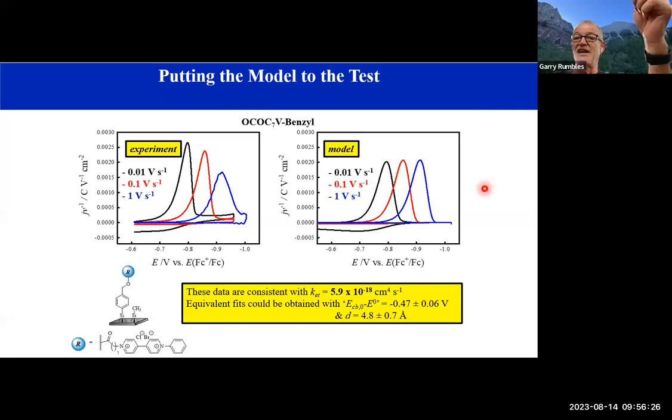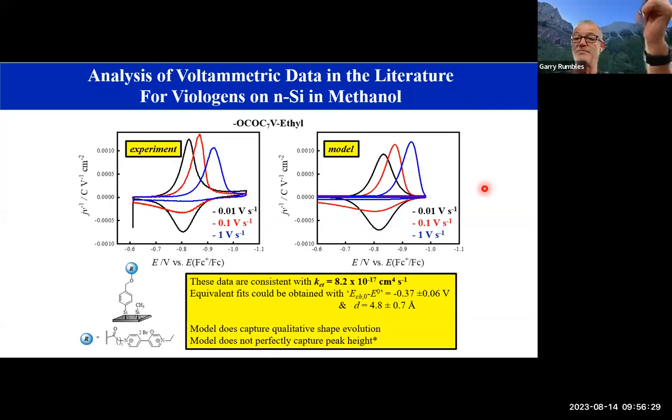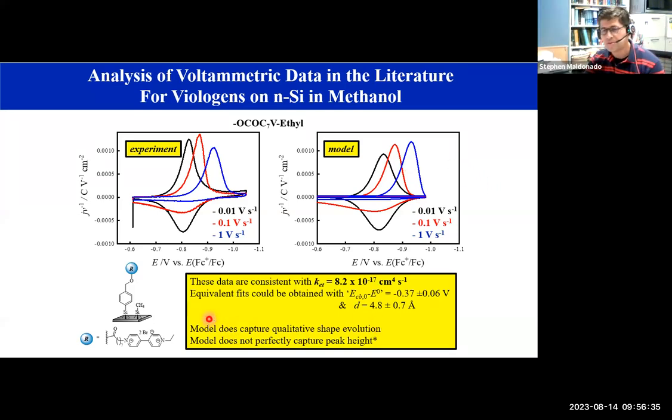So D is a layer on the electrode surface, isn't it? Yeah, that's the one. So what is 4.8? As we are both modeling and interpreting, we're trying to get molecular dynamics to get some firmer confirmation. But this tether, which is not immediately obvious from the picture, is actually pretty floppy. Okay, so you have a linear alkyl chain. That entire tether length is much longer than that distance. There's no through-bond tunneling in this case. What happens is the molecule bends over, and we think on average that's the average distance for charge transfer.